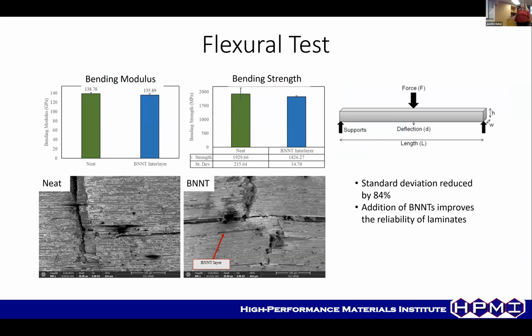So you can see the addition of the BNNT layers inside. We also did interlayer ones. BNNTs on the interply reduced the standard deviation of the bending modulus and strength by around 84%, but didn't really change the properties. That's not necessarily a bad thing, because we don't have increased modulus or strength, but we don't have a drop either. But we have a significantly reduced standard deviation.